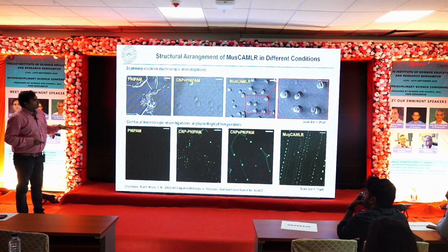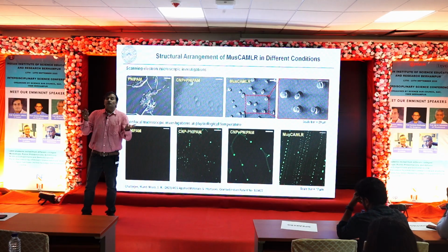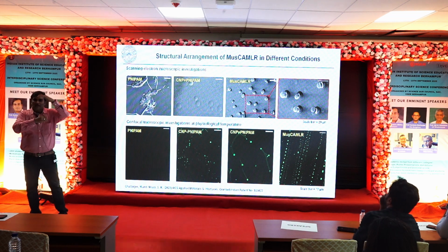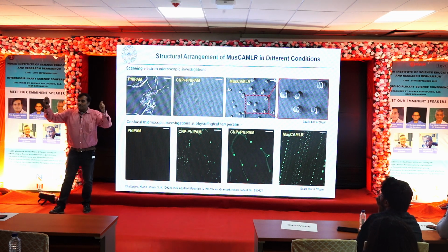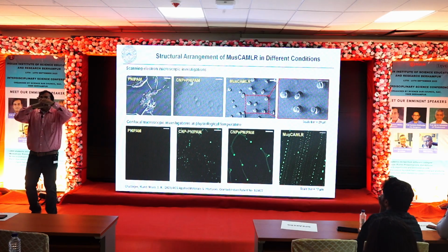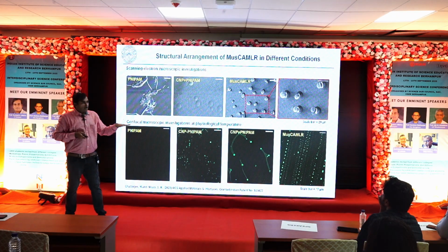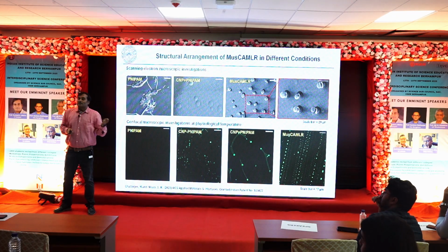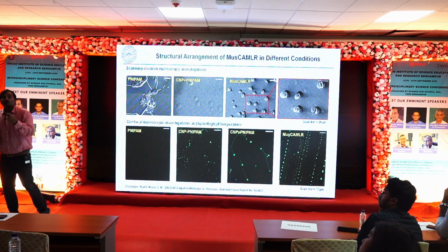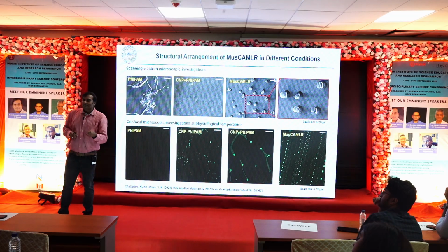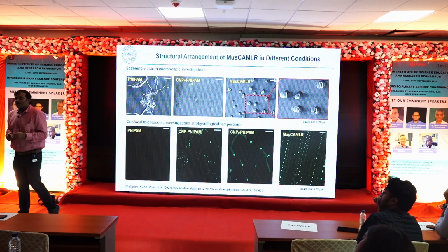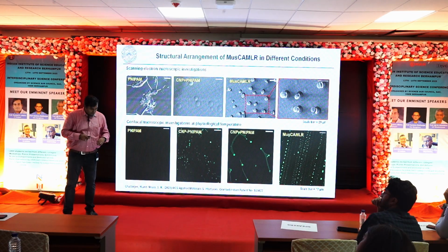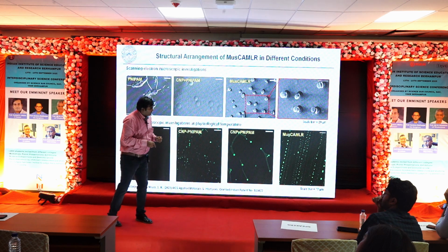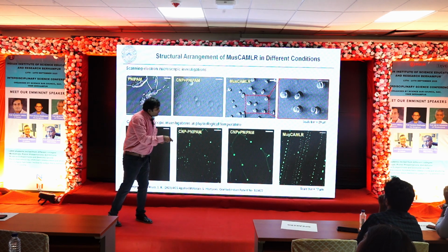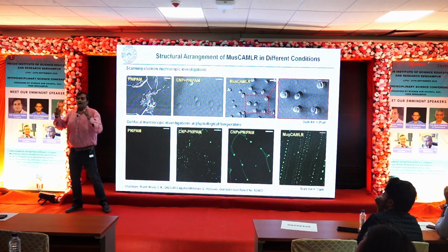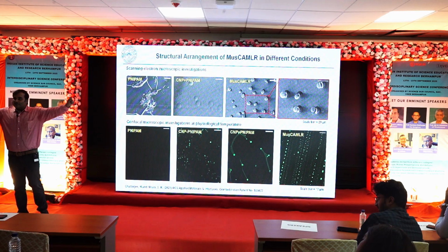We also tried to look at whether that alignment can be seen or not, right? Whether this PAM polymer and the carbon material along with the passivated material are making that kind of sliding network or not. We found that they were, and we could trace it because these carbon particles had another unique property called autofluorescence. So they fluoresce. If you excite them at 350, 390, 400 nanometer, they give green fluorescence. So we could follow it. Now you can see a bunch of these particles together and they are making a certain alignment, which says that they are actually being integrated in the polymeric system of PAM.